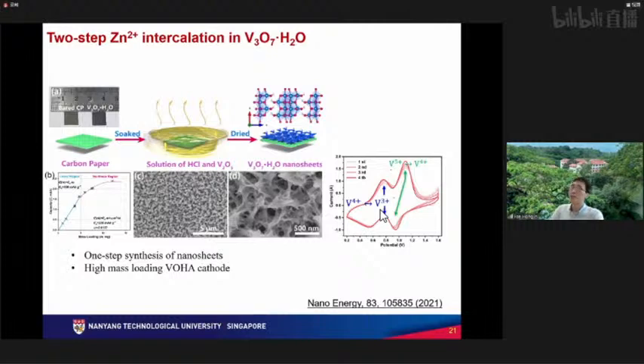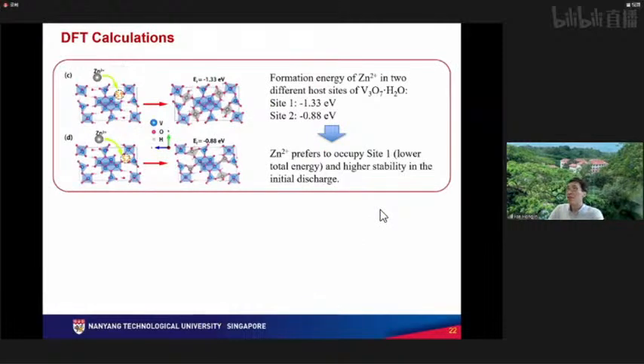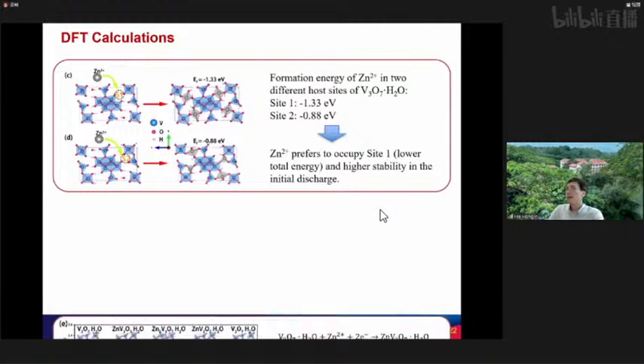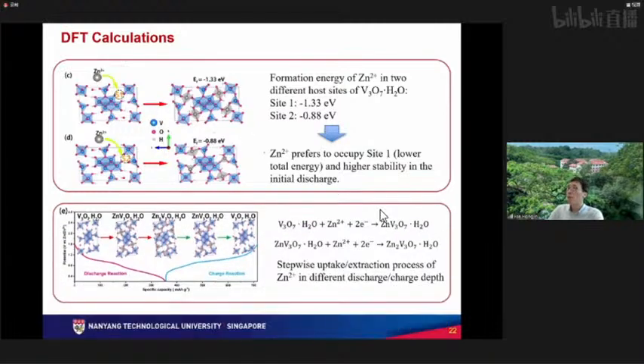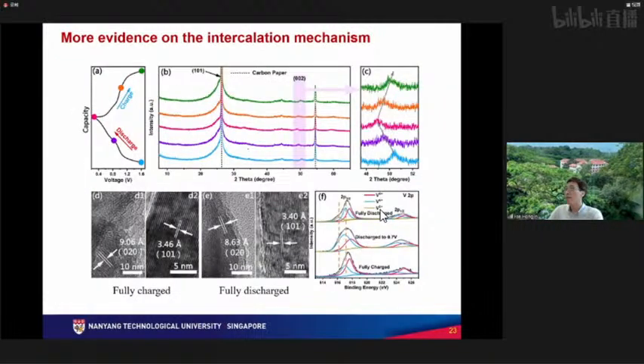Although this kind of redox peak actually is very common for other vanadium polymorphs, right? So they also did a DFT calculation to confirm how zinc ions go in and out, and found that the zinc ion prefers to occupy site 1, corresponding to the lowest potential energy. And if you do ex situ Raman, XRD, as well as ex situ high resolution TEM to confirm the crystal phase, it is a reversible crystal phase. And then we do fully charged, and somewhere in the middle, the XPS finds the peak is coming back after charging, and the XRD peaks are also reversible. Okay, so this verifies the two-step redox peaks of vanadium because of vanadium-5.